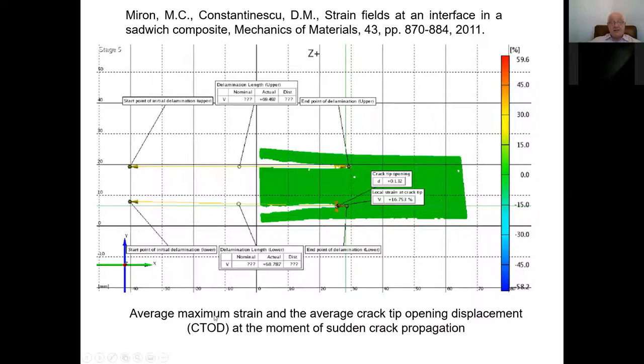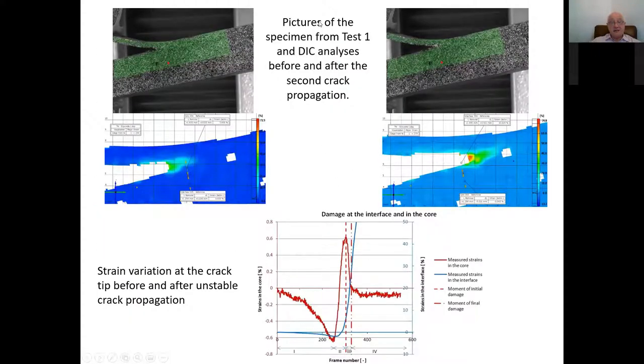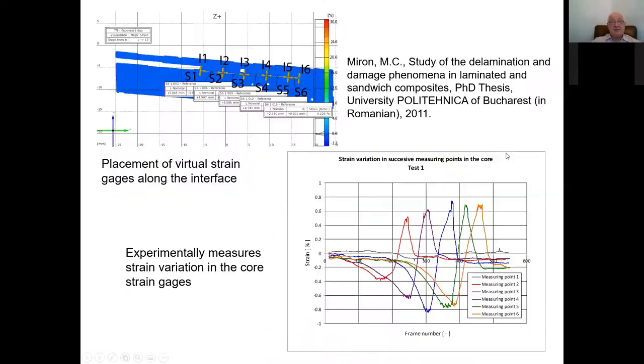Of course, we were interested to look for the strain fields. If you have precise measurements, you can establish what is happening when the crack starts to propagate, and here you have two curves, one showing the variation of the strains in the foam, and the other, let's say, along the interface. So what I'm trying to say is that this type of DIC analysis is very useful for looking at damage initiation and even propagation.